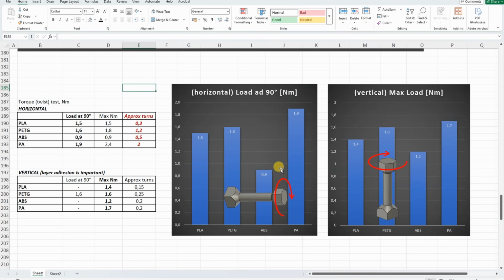These are good values except for the ABS. Now printed in vertical position, again very similar numbers like with this one printed in horizontal position, and even the ABS is, let's say, acceptable here, but I was expecting a little bit more from this material.